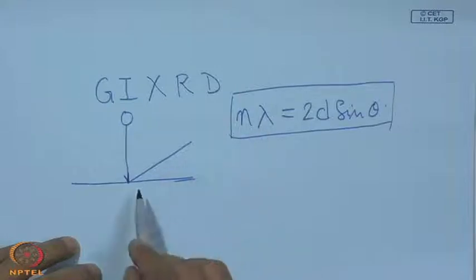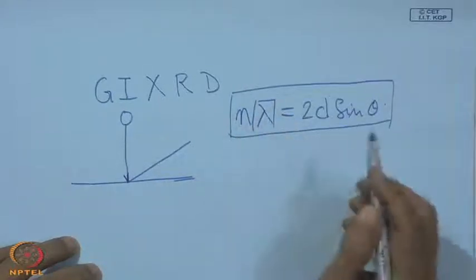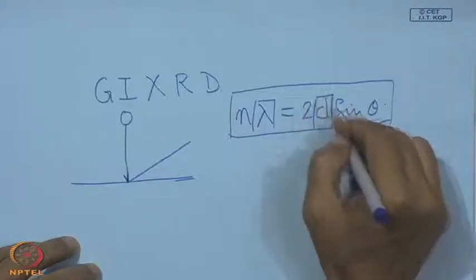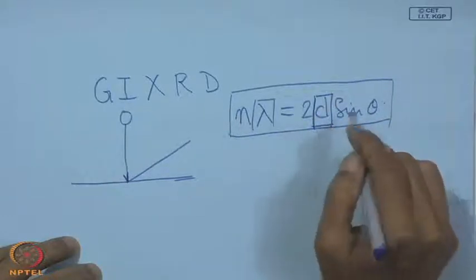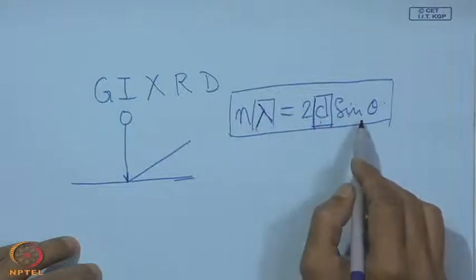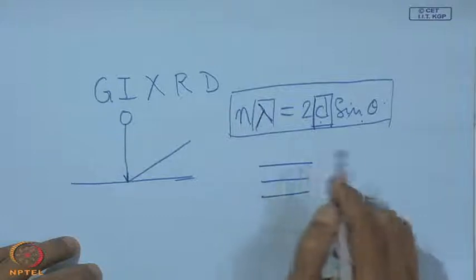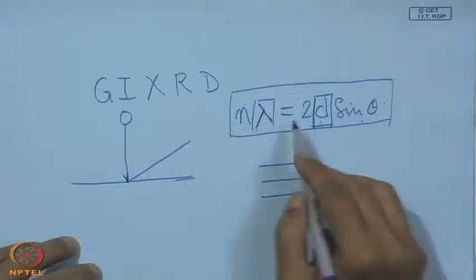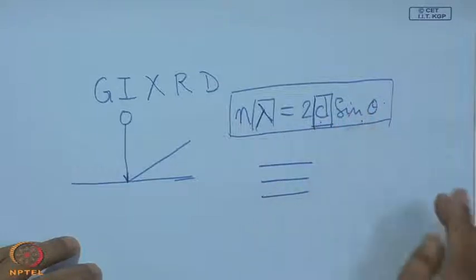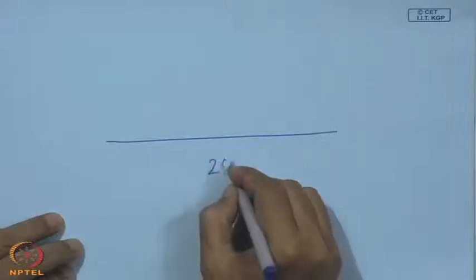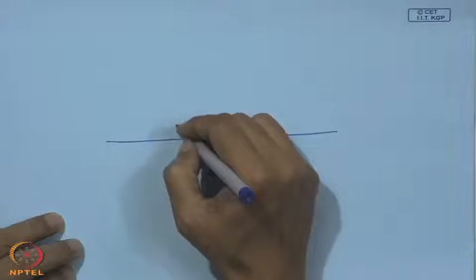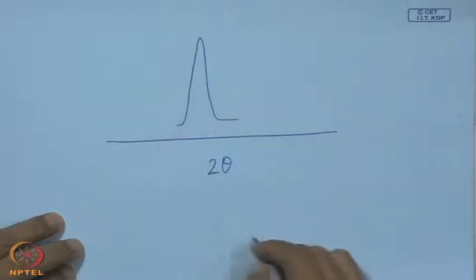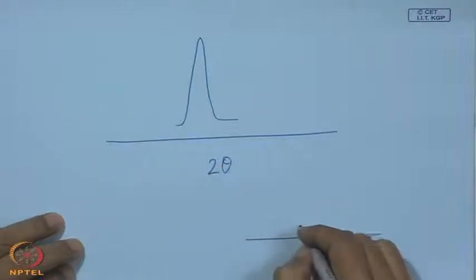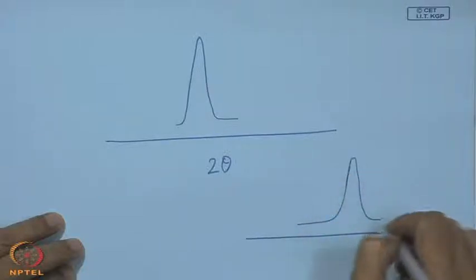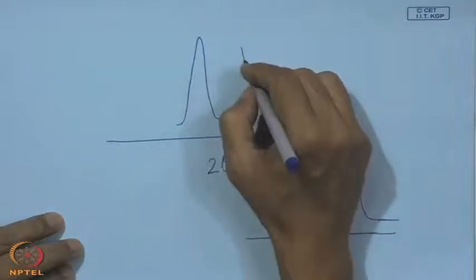Now, depending upon the element or the phase, the value of lambda will change, and since it is actually the 2d, that means the spacing. Now, depending upon the crystallographic spacing, this lambda will be connected with 2d and sin theta. That means, if this d, the spacing, changes, then a particular value of d is connected with this sin theta, and accordingly in the XRD diagram, where we put 2 theta, we can get typical peaks which show the very existence of a particular phase. So, this is also typical of a particular coating, say for example, WS2.